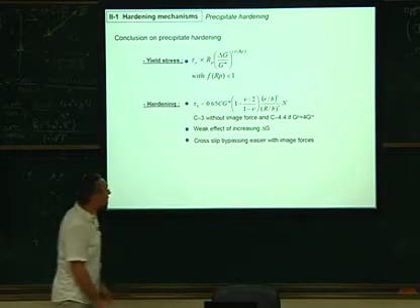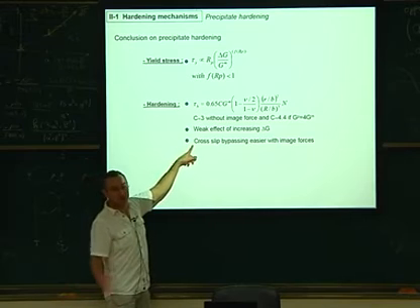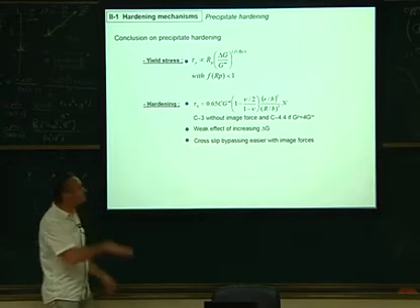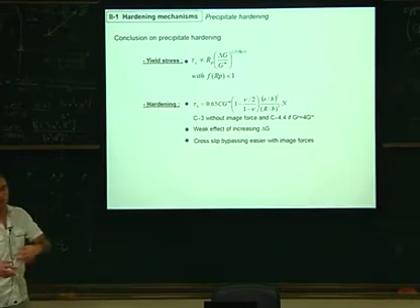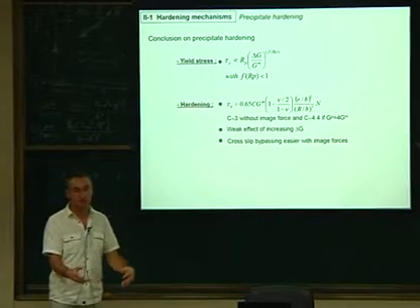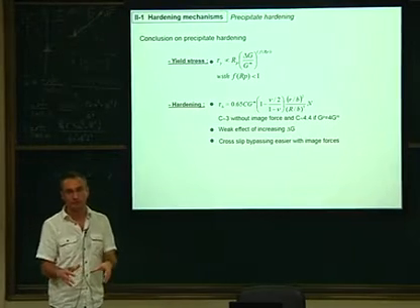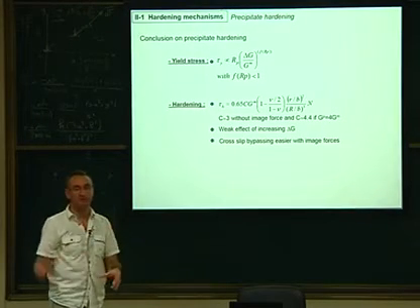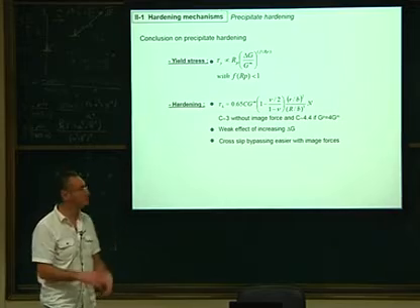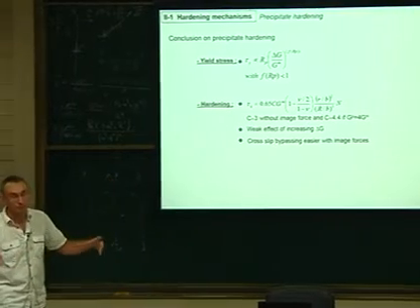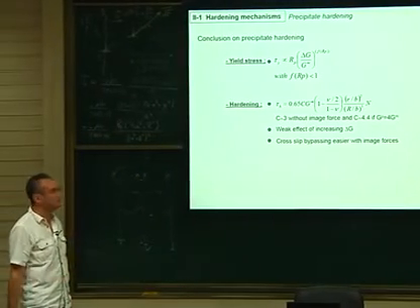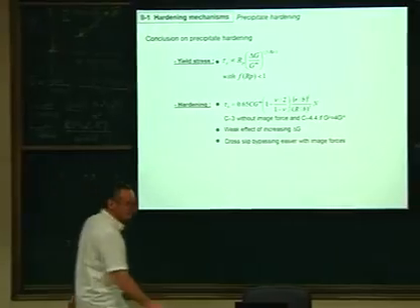Okay? And of course, there is the cross-slip that can recover, that can decrease this effect a bit after a few loops deposited. Usually after 2 loops or 3 loops, the 4th loop is cross-slipping and going away. It cannot stay there. So it's very rare that you have 4 or 5 loops surrounding the particles. This is impossible if it's non-shearable particles.